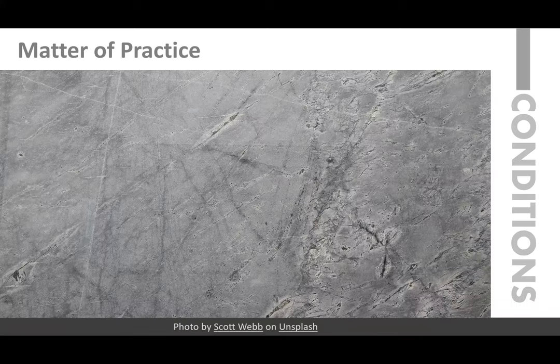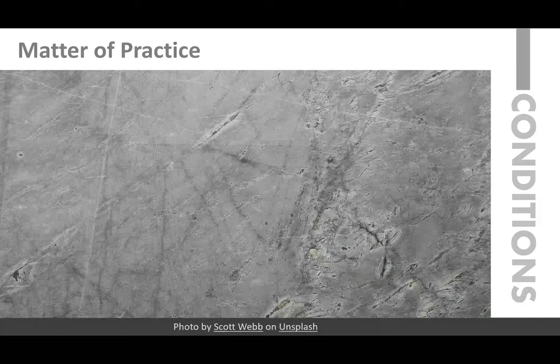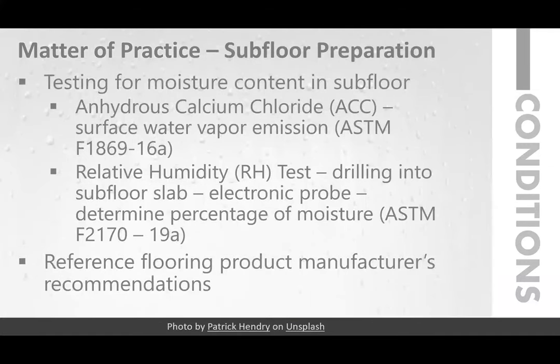An important part of successful installation is understanding project conditions. No matter what type of resilient flooring product is installed, subfloor preparation is key. The preparation involves measuring moisture content in concrete slabs and selecting a condition-appropriate adhesive. There are two test methods: the anhydrous calcium chloride test, which measures surface water vapor emission, and the relative humidity test, which drills into the subfloor and uses an electronic probe to determine percentage of moisture.